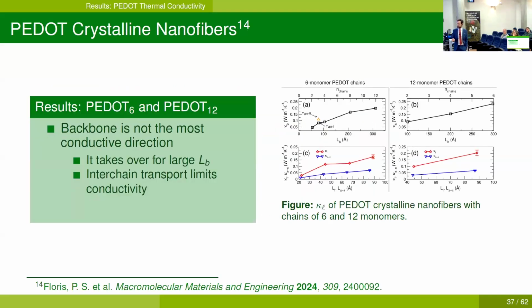Moving to the results, let's first discuss 6 monomer PEDOT chains here. When we look at the lattice thermal conductivity along the backbone here, we can see that it's increasing as a function of the length of the nanofiber. Why? This is an artifact of molecular dynamics techniques because basically what we are seeing is that the boundary scattering is prevalent in the sample, but when we increase the length of the nanofiber, we see that the boundary scattering will become less and less relevant.